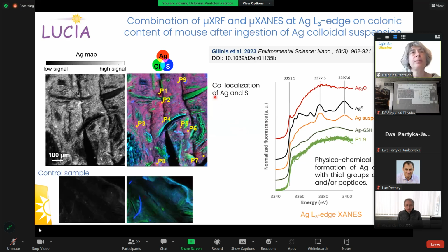Then metals can be ingested. Here is a study of the ingestion of colloidal silver suspension by mice and what happens in the colon of these mice, as the users have demonstrated that the colon is damaged by this ingestion. And here you have an XRF image of the section of the colon. And you see with the map of silver and sulfur that they are colocalized, and with the XANES at the silver edge, that in fact the silver changes its speciation to form complexes with the thiol groups of proteins or peptides.